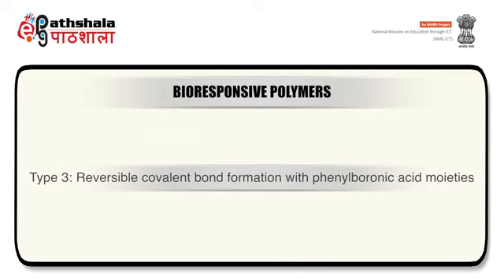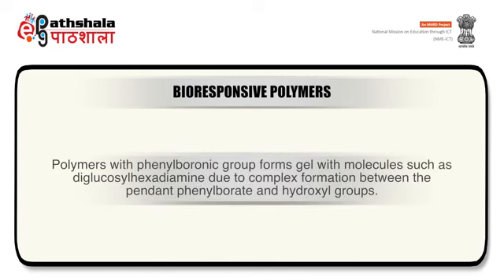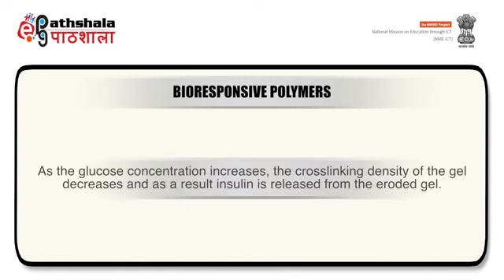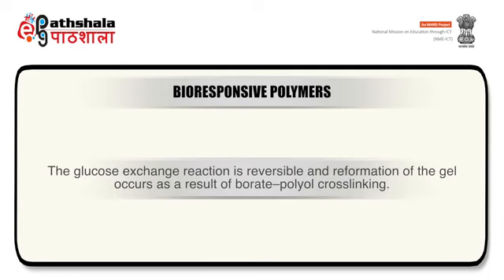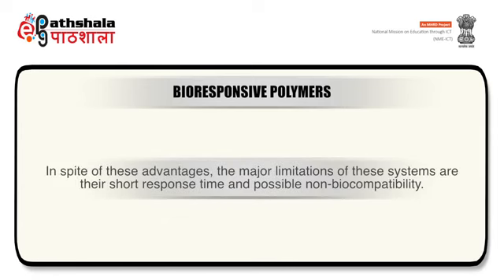Type 3 systems are based on reversible covalent bond formation by phenyl boronic acid moieties. Polymers with phenyl boronic groups form gel with molecules such as diglucosyl hexadiamine due to complex formation between the pendant phenyl borate and hydroxyl groups. As the glucose concentration increases, the cross-linking density of the gel decreases, and as a result, insulin is released from the eroded gel. The glucose exchange reaction is reversible and reformation of the gel occurs as a result of borate polyol cross-linking. In spite of many advantages, the major limitations of these systems are their short response time and possible non-biocompatibility.